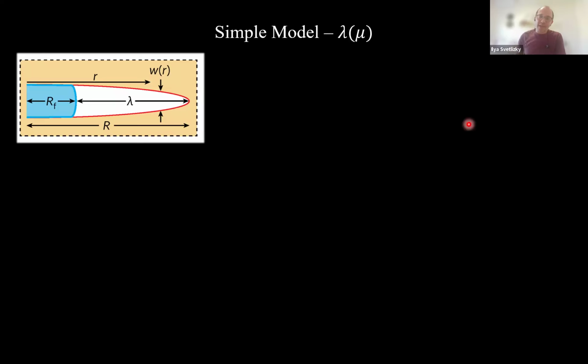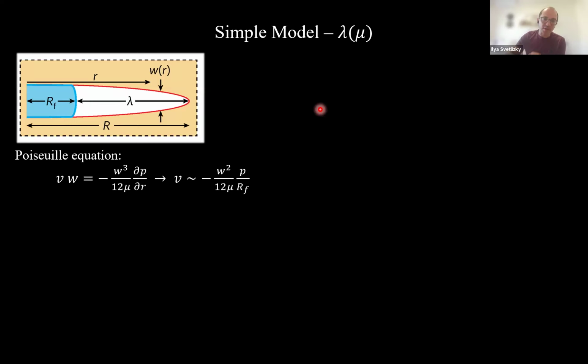Good. So the next step is I want to give some sense why the lag between the crack tip and the fluid front depends on the viscosity. So again, a heuristic argument, you have a Poiseuille flow. Poiseuille flow is that the average velocity of the fluid times the crack opening is the flow, depends inversely on the viscosity mu and depends linearly on the pressure gradient. Again, this is the scaling arguments.